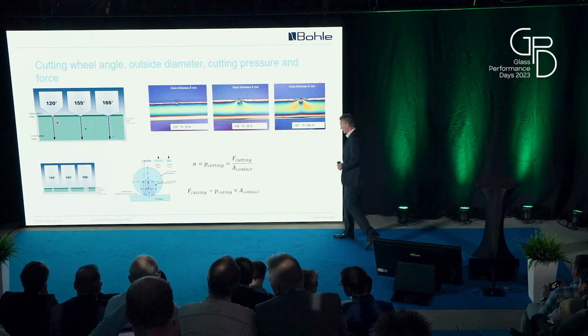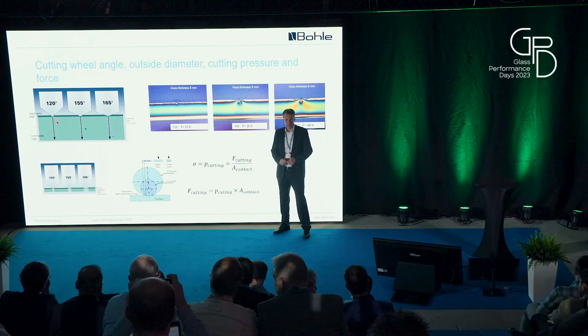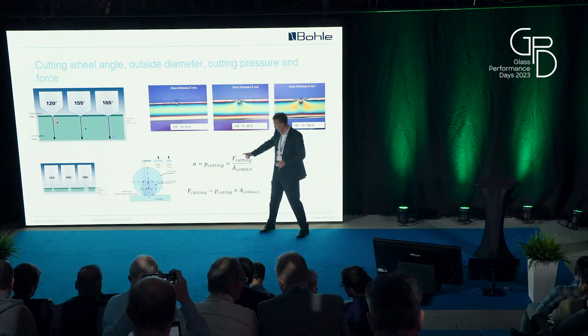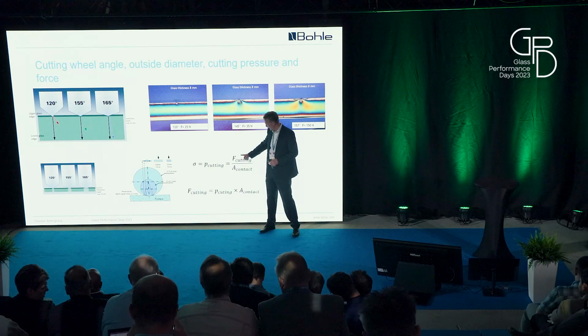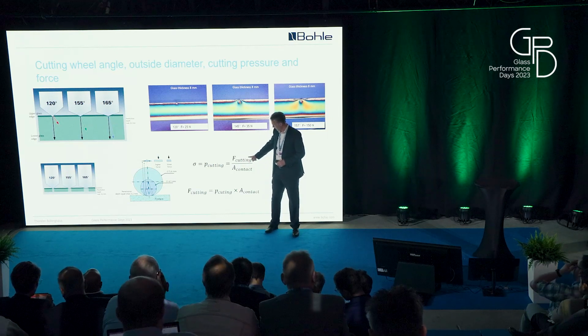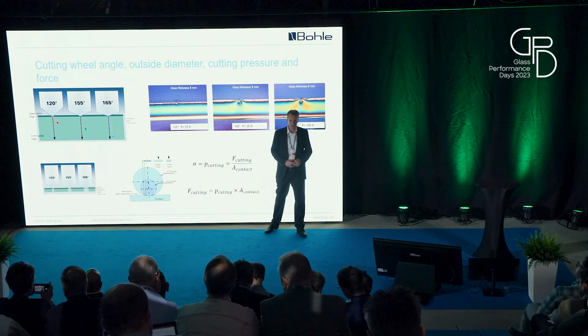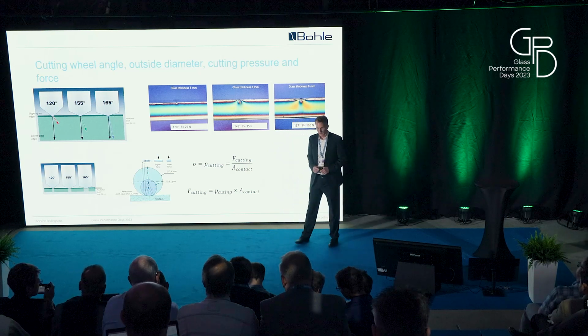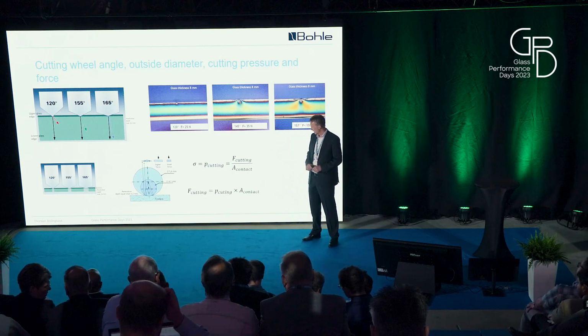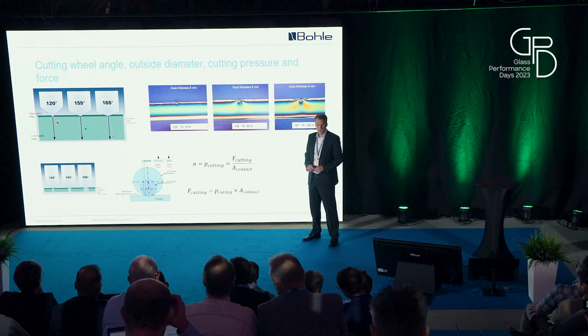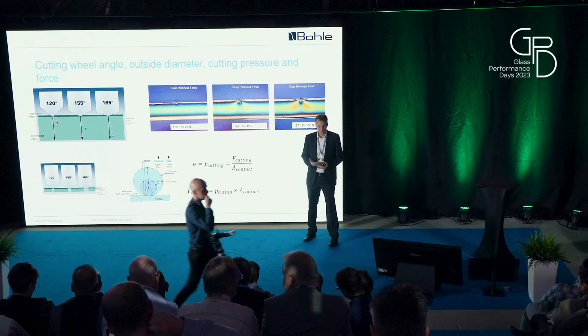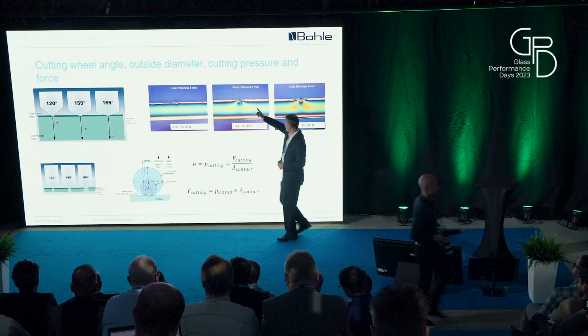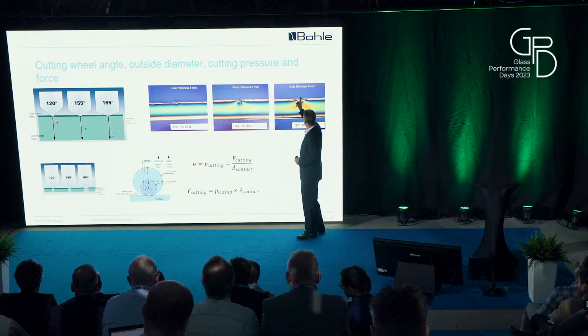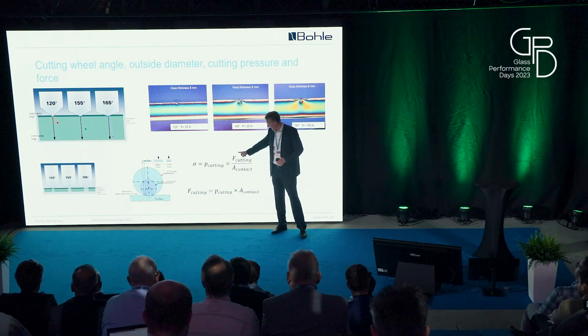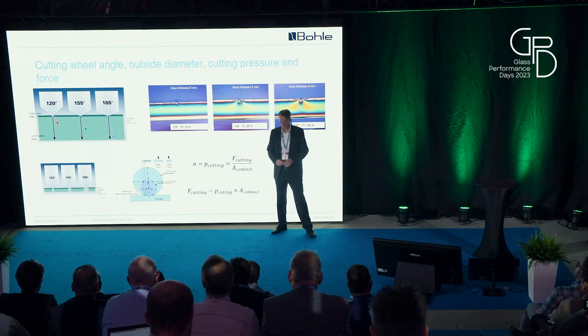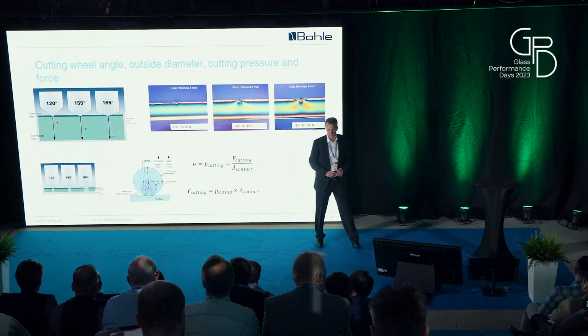In the contact zone of the cutting wheel with the glass surface, you have the cutting pressure. And if your cutting force, which you divide by the contact zone, the contact area, the surface that you have with the wheel and the glass, is too high, then you will damage the surface of the glass. That's what you see here and there.